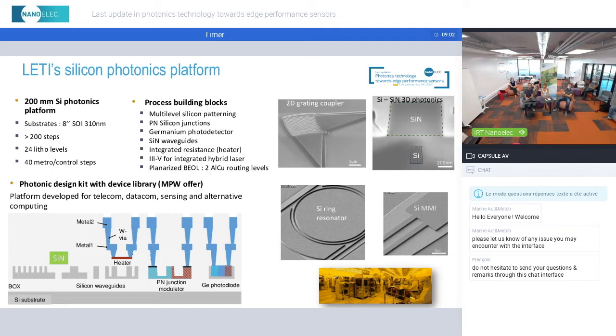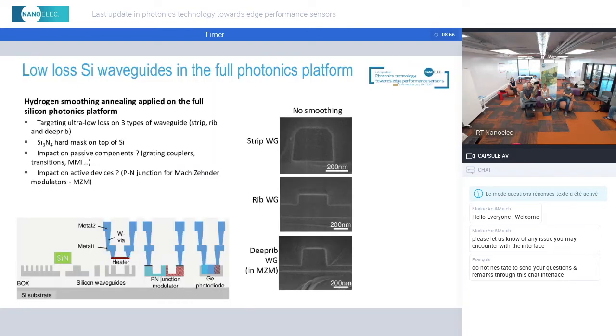Okay, so let's see now the results. When we apply this hydrogen annealing to the full platform, we target very low propagation loss for all the types of waveguides that we use. So the strip and rib waveguides, you can see the cross sections here, already mentioned by Erwin, but also the deep rib waveguide with a thinner slab that is used in the Mach-Zehnder modulators as a good compromise between optical mode confinement and electrical access.